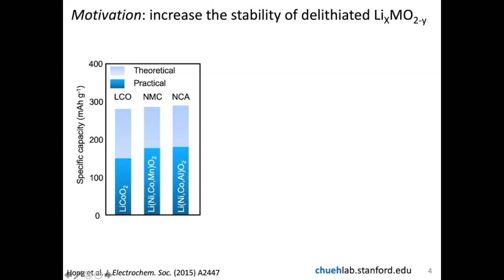So let me begin by reminding everyone the motivation for the lithium-ion battery cathodes. One of the biggest challenges is that as you remove lithium, the stability of the material decreases dramatically. And this is why we typically can only remove about half of the lithium from cathodes like lithium cobalt oxide, the NMC materials, and NCA materials. And this has a significant limitation on the energy density. So this plot just shows you the opportunity for increasing energy density by allowing you to delithiate further.